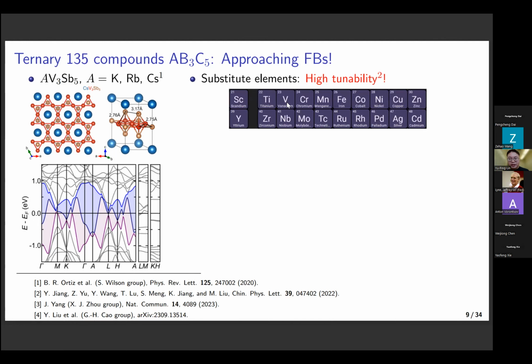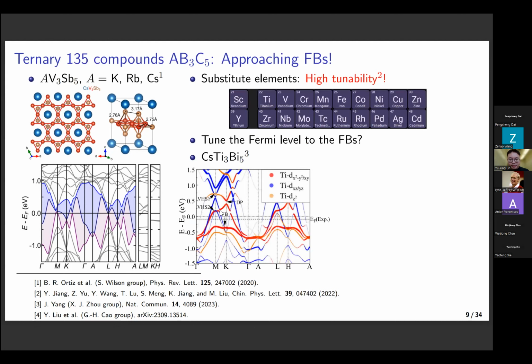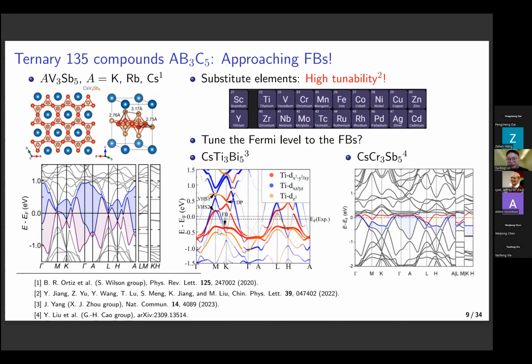For example, if we look at the periodic table, we can see that the vanadium atoms are here. If we substitute it by, for example, titanium or chromium or manganese, then we can possibly change the Fermi level to the other fillings of the kagome band. And indeed, it has been realized recently in other materials. For example, in the titanium-based materials, because we are going one electron lower in the periodic table, the Fermi level is tuned below, and it is actually approaching a lower flat band in the band structure. And more recently, actually within the past month, there is a chromium-based material where, because chromium is one electron higher than vanadium, the Fermi level is tuned upper, and it is actually approaching the upper flat band of the band structure.